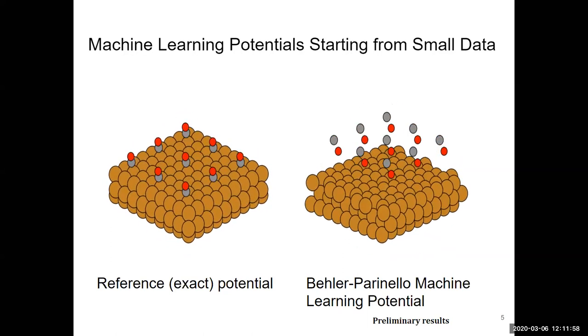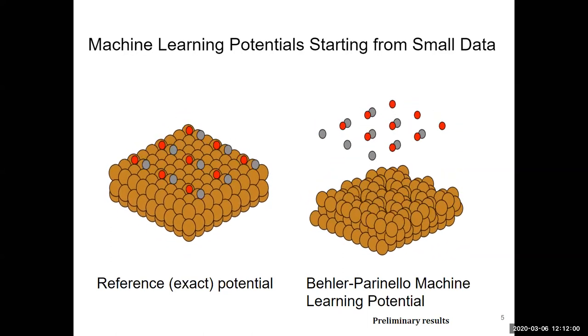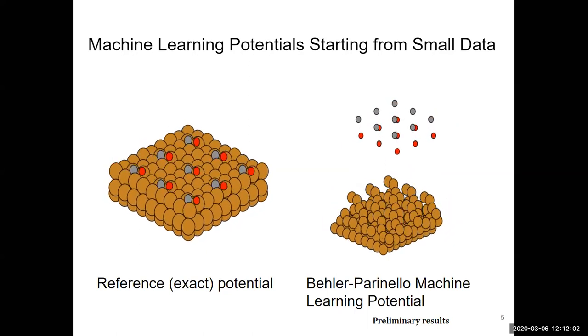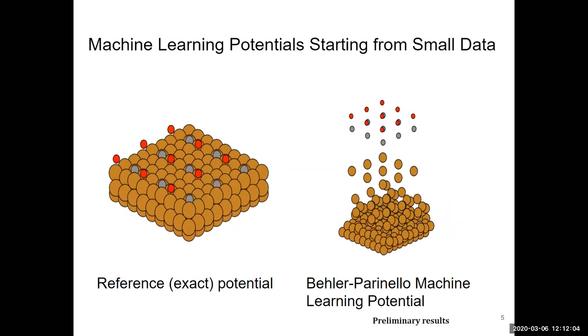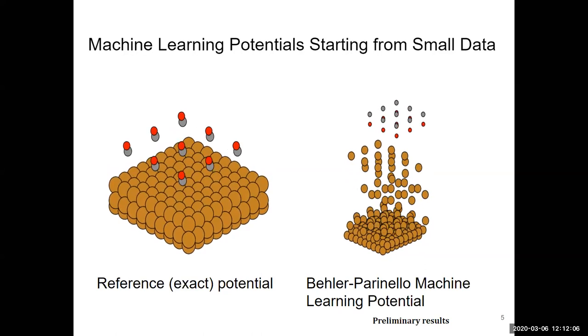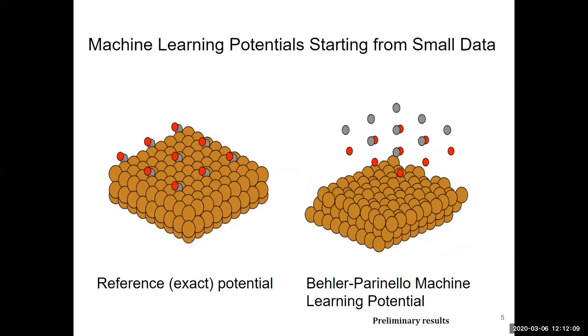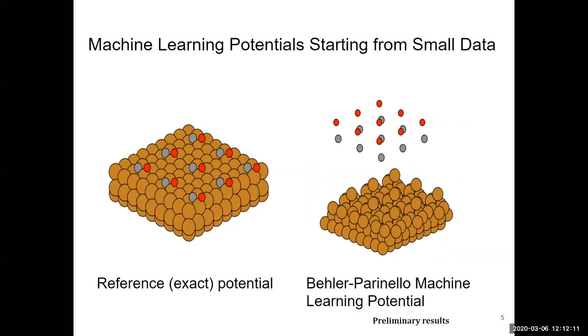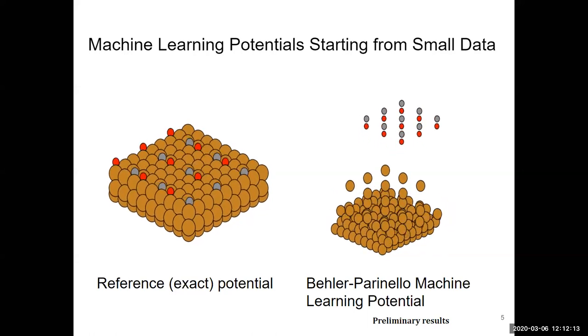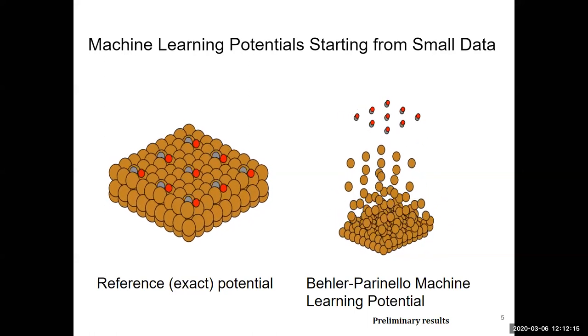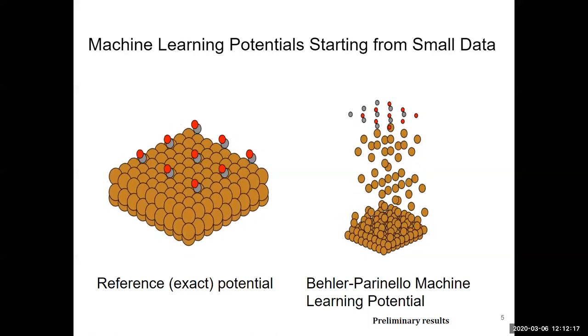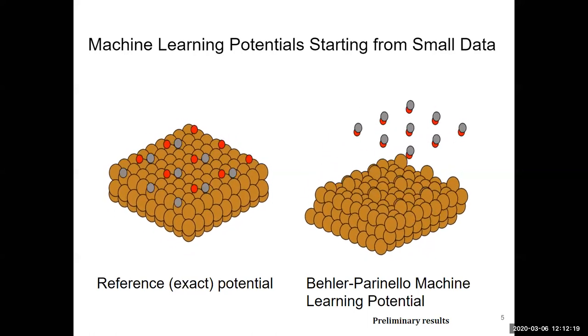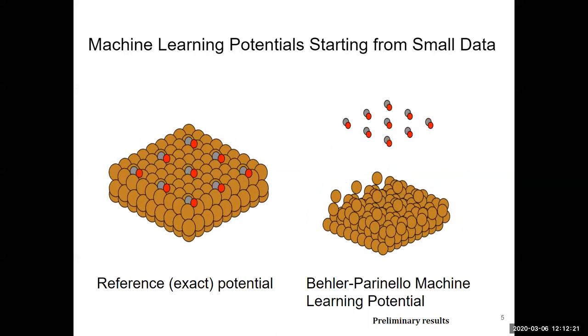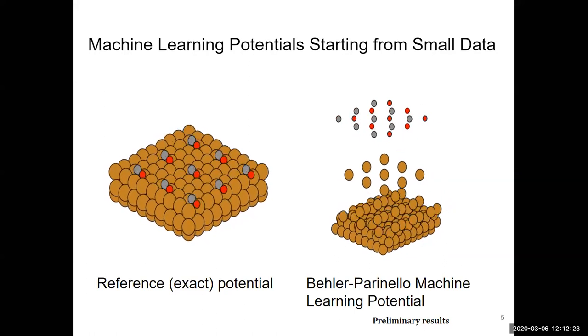And this makes it really, really complicated to fit these things in an online framework, because if you're trying to sample from this distribution, I can't even get DFT to converge in those places, right? If you have two atoms overlapping, you're not even going to be able to solve the electronic structure problem. Even if you do solve the problem and you add the data, that's probably going to poison your data set. And those aren't things that you actually need to care about. I don't need energies in my data set that say two atoms overlapping are super high energy.